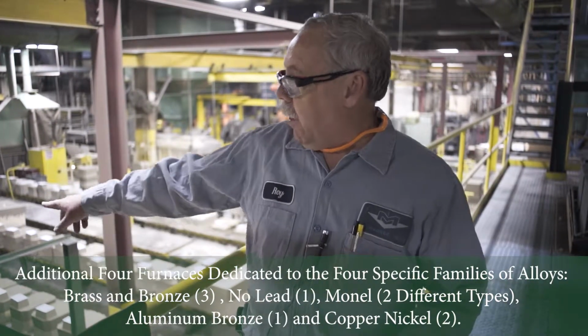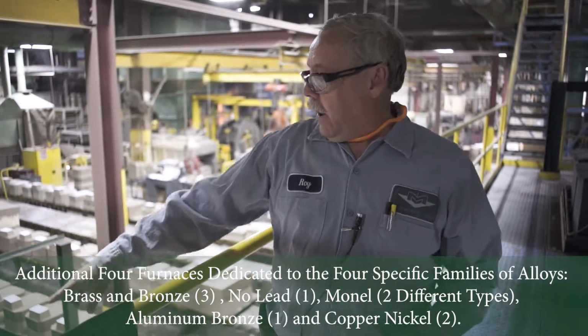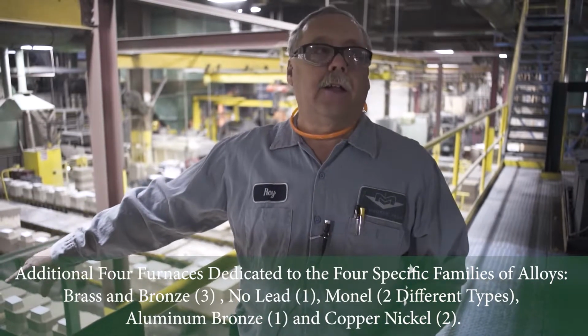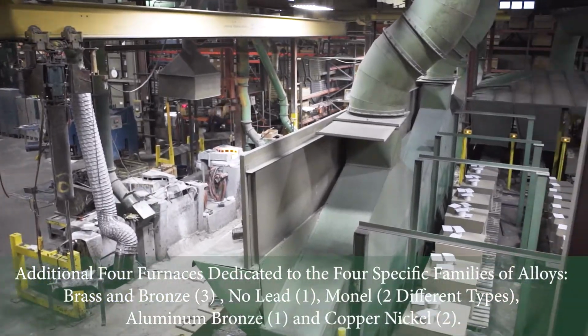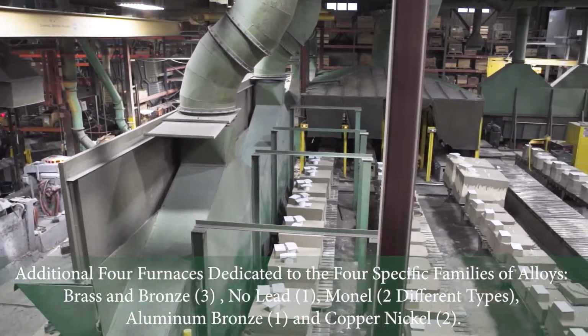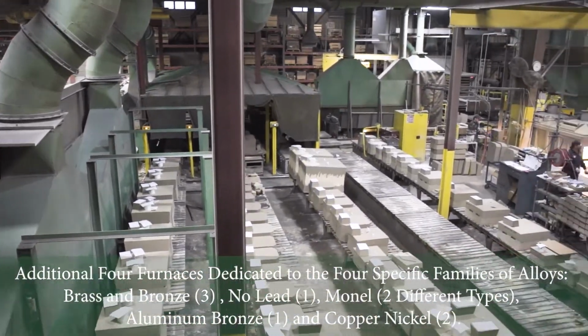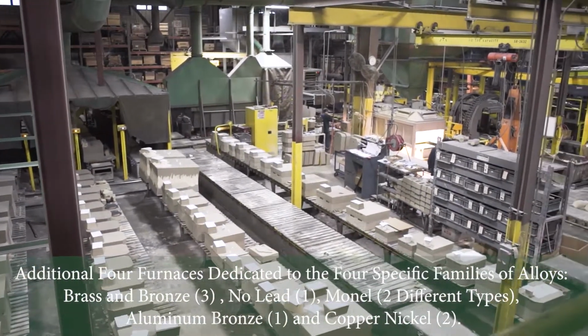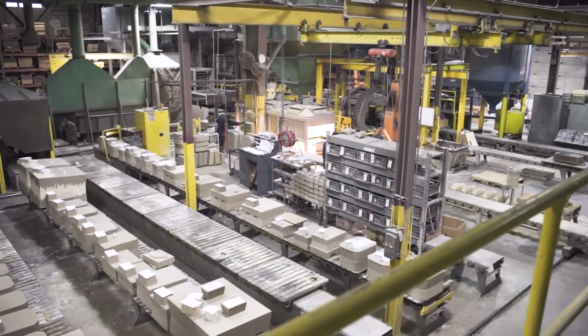It clamps up the mold, it's ready to pour, and the molds with the weights on, you'll see down there, have the test bars. That's where the test bar molds are poured. So on this molding line, we have the ability to melt about 10,000 pounds of bronze an hour.